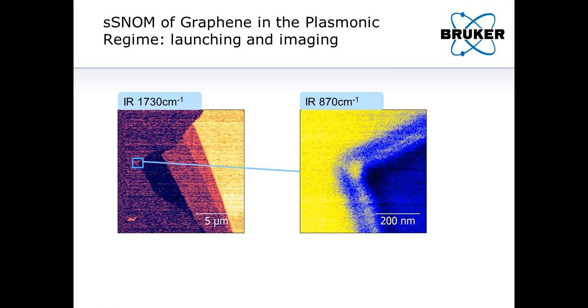So this 10 hertz image is obtained in just 60 seconds, and we did not have a significant loss of spatial resolution. And we believe that this is probably the fastest image of a nanoplasmon in graphene obtained to date.